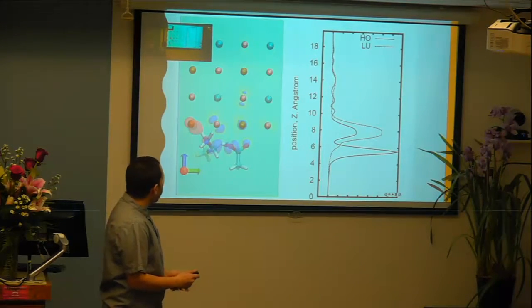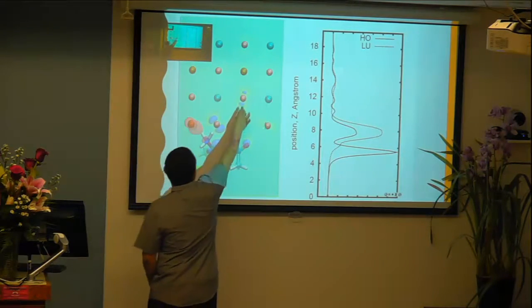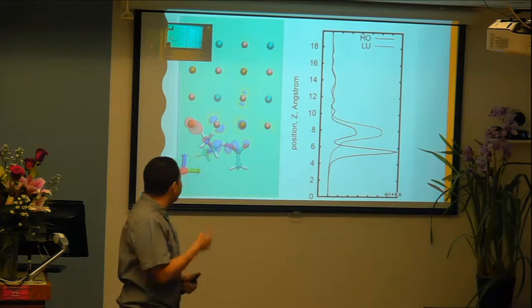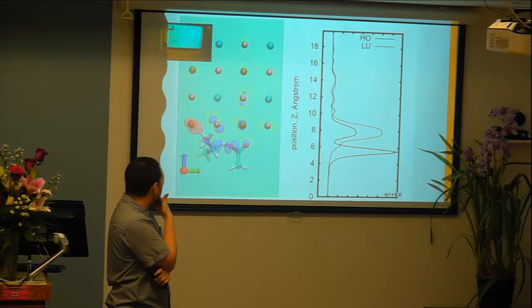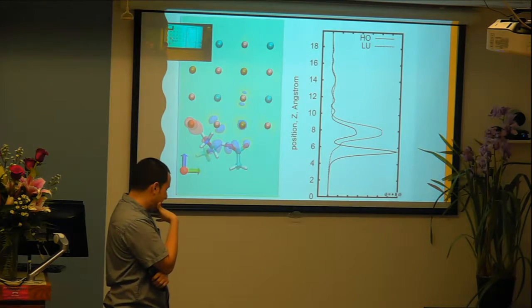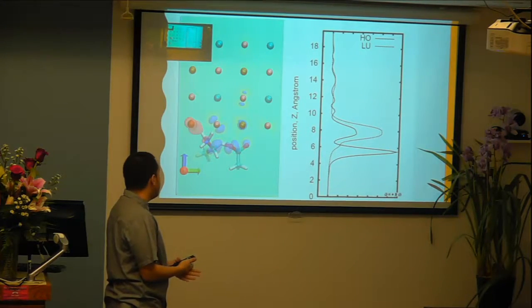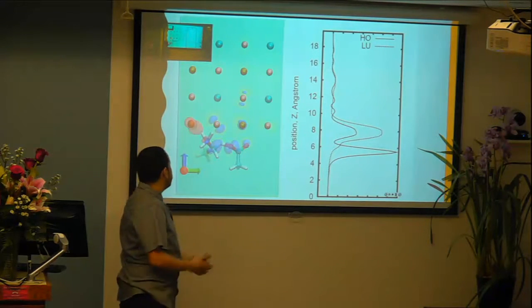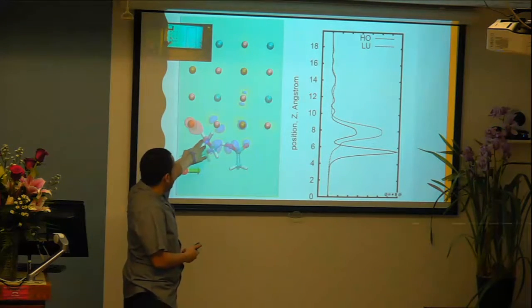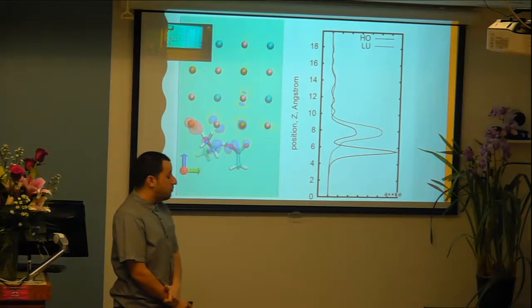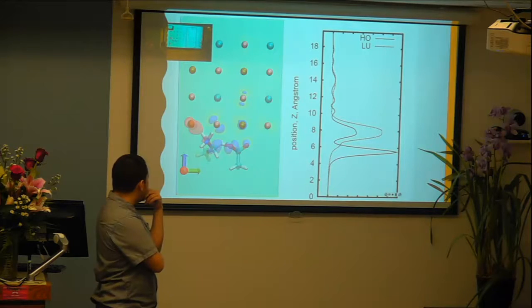One thing that was a little tricky for me was that I have no idea how I ended up getting a HOMO orbital in the middle of my surface. That was something I've got to look into, and look at more of the orbitals and levels. I only got a chance to look at the HOMO and LUMO due to time being an issue. But besides the point, we also did find LUMO orbitals on the surface of the structure, along with some on the methylamine, particularly on the amine site, which is kind of interesting to look at.